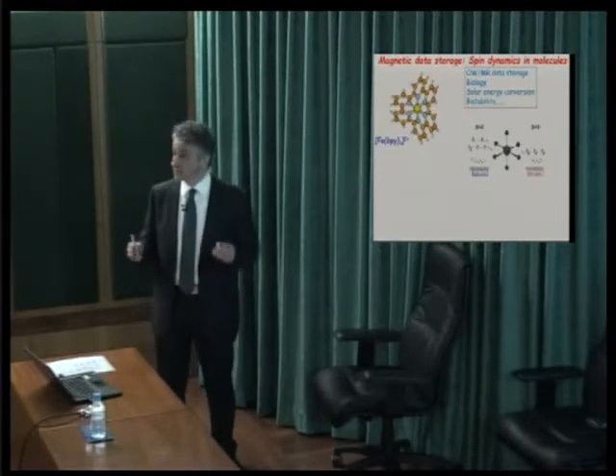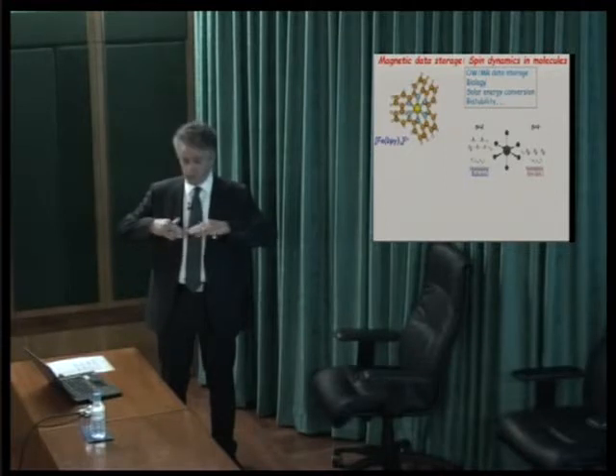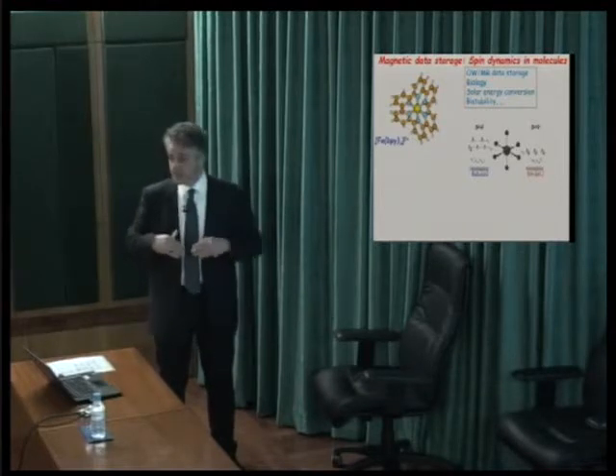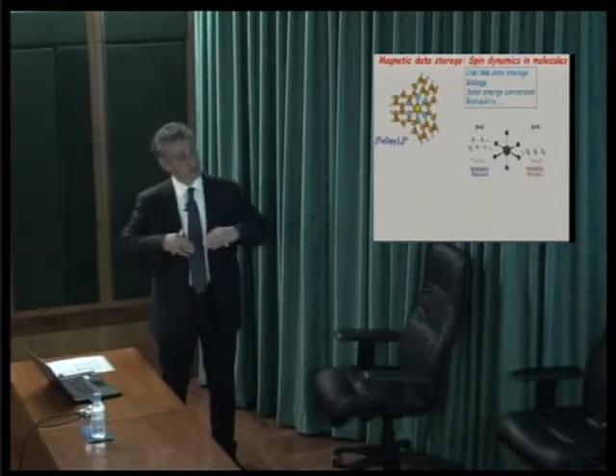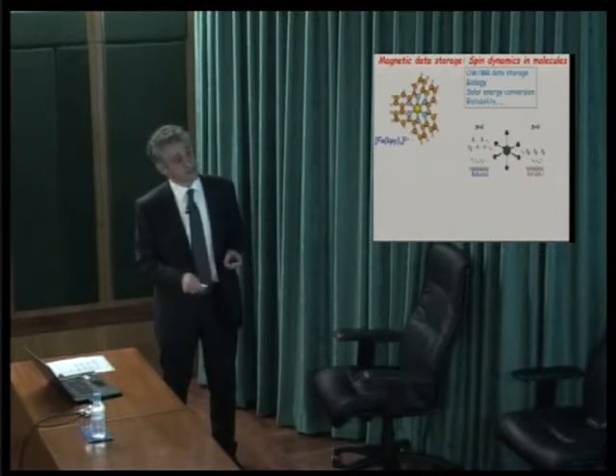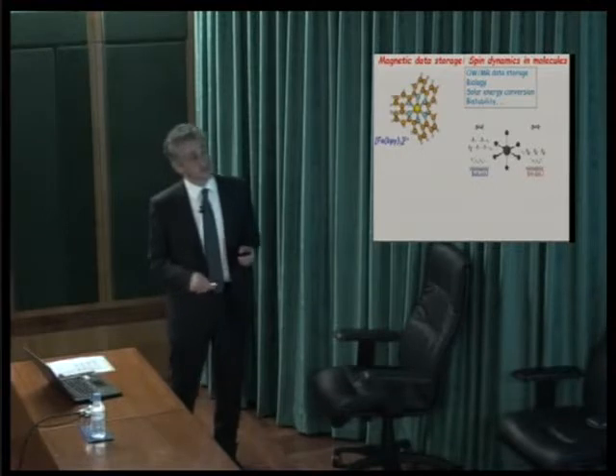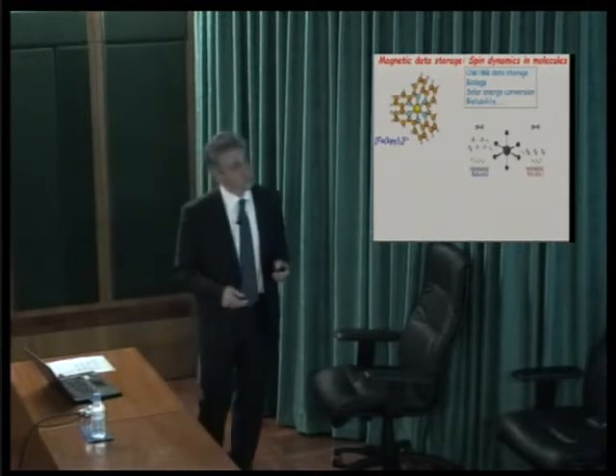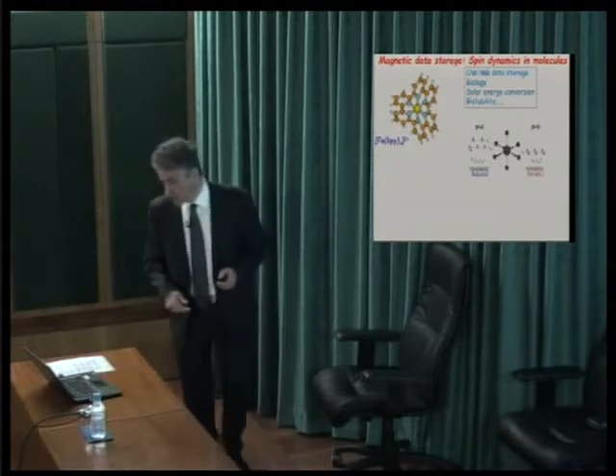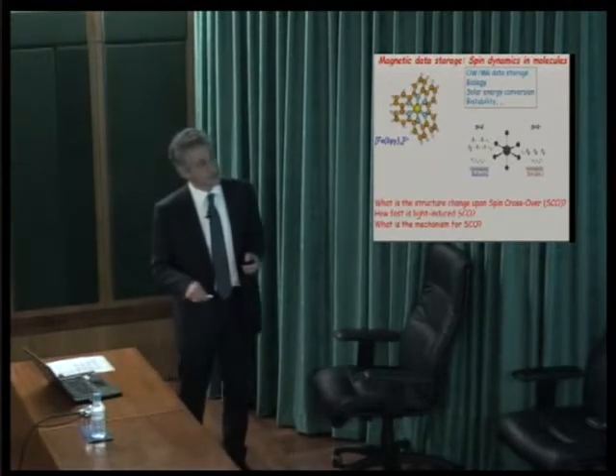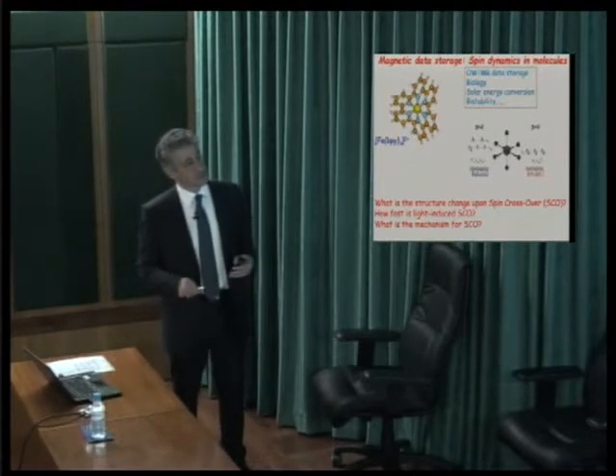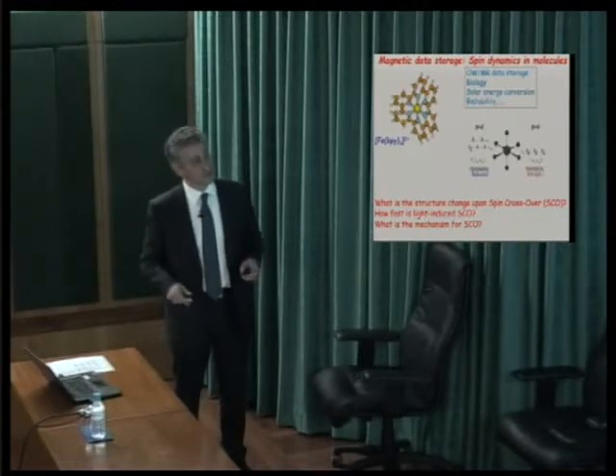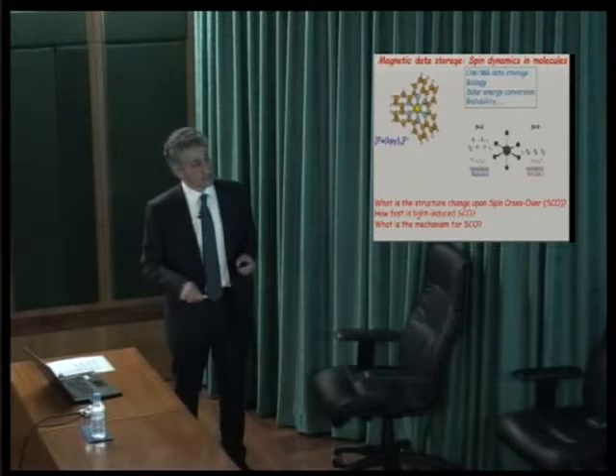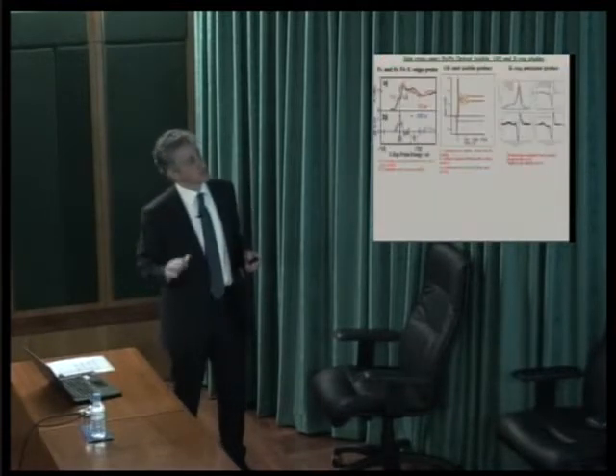In biology, by the way, when you breathe and you go from the planar to the domed porphyrin, the domed porphyrin in our hemoglobin is a high-spin iron complex, very similar to that one, whereas the planar is a low spin. And actually, it's the same spin change. For solar energy conversion and bistability of magnetic molecules, this is also a very hot topic. So when we started, we were interested in understanding the structure change upon crossover, because you are going from a low spin with only bonding orbitals to two electrons in the antibonding orbital. And then what are the mechanisms for the spin crossover and the time scales? I don't want to go too much into details.